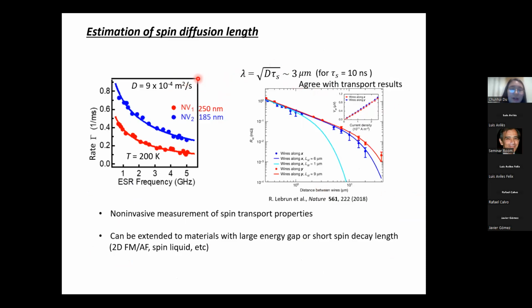So to further understand what this spin diffusion constant means, we can use it to estimate the spin decay length, which is the square root of the spin diffusion constant times the spin relaxation time. If we estimate the spin relaxation time, it's around 10 nanoseconds, which is typical for magnetic material. So we can see that the spin decay length is about 3